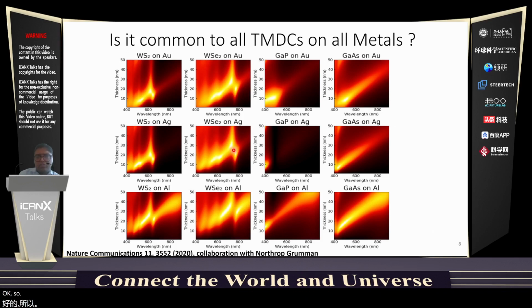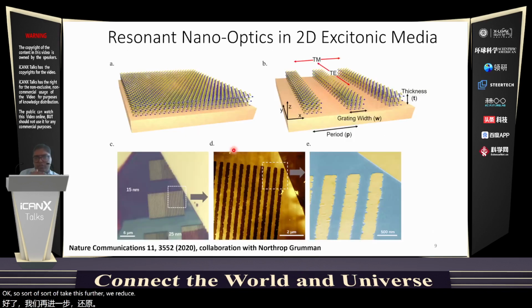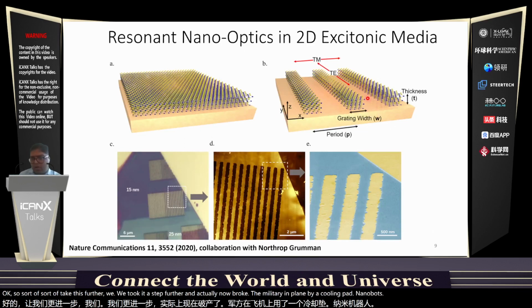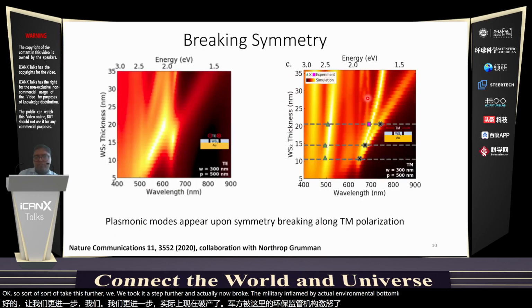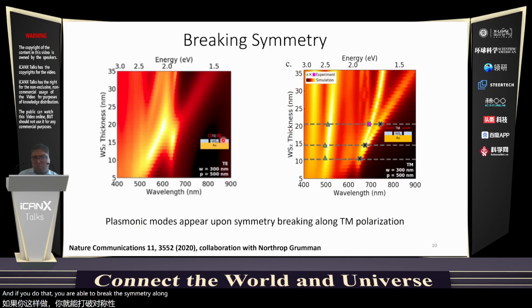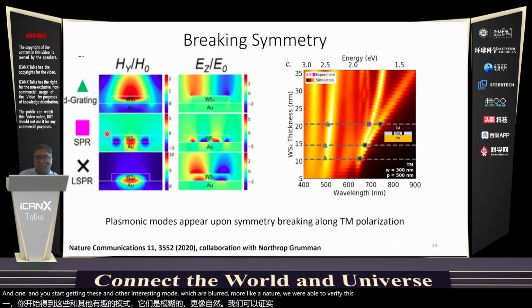Okay, so to take this further, we took it a step further and broke symmetry in plane by nano-patterning resonators over here. And if you do that, you are able to break the symmetry along one direction and preserve it along the other direction of polarization of light. And you start getting these other interesting modes which are plasmon-like in nature. We were able to verify these modes are plasmon-like in nature by doing FDTD simulations.